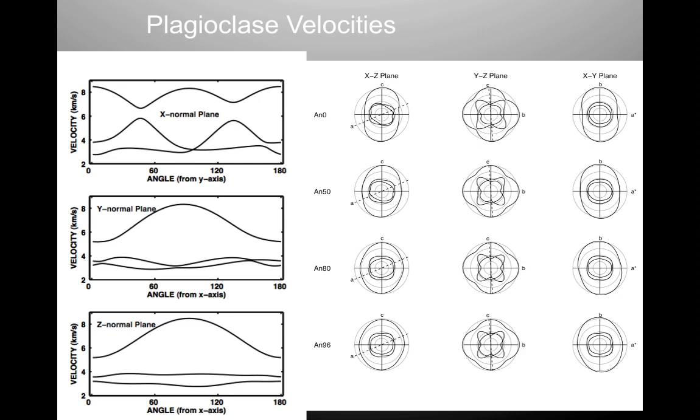If this were an orthorhombic crystal, there would be a mirror plane through C, and there'd be a mirror plane through the horizontal axis. And I draw in where orthorhombic crystals would have mirror planes. And you can see that there are deviations from orthorhombic symmetry, but perhaps they are not so large. And you can overall see an imprint of orthorhombic behavior to the elastic constants.